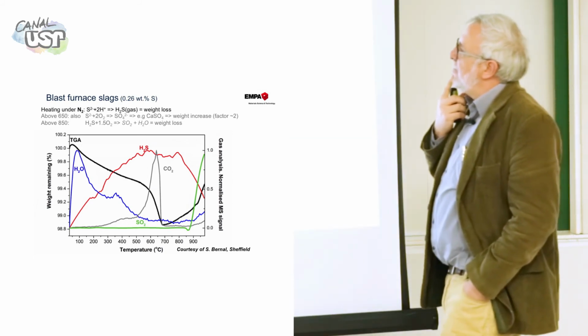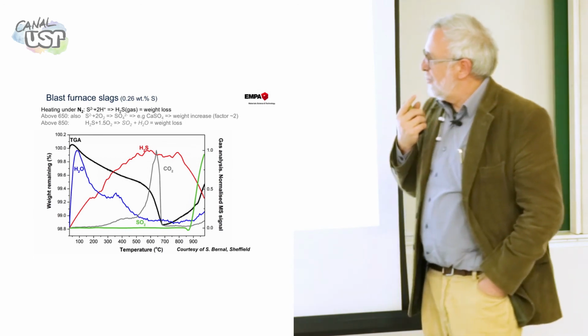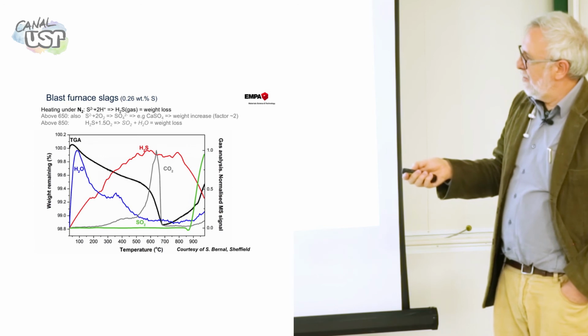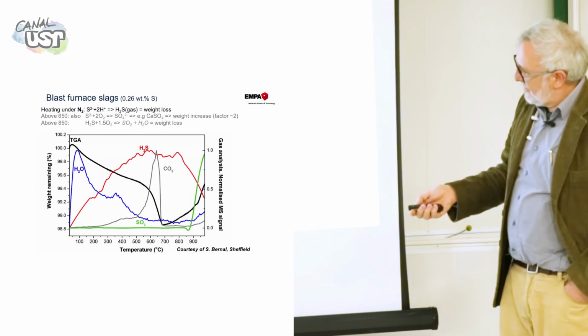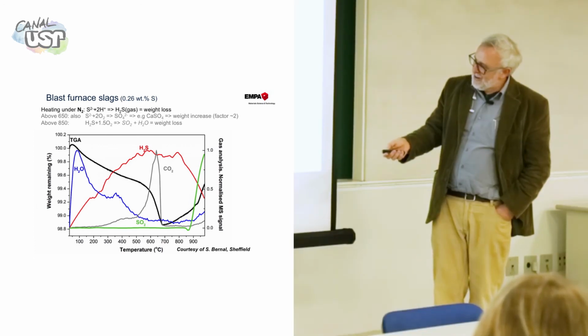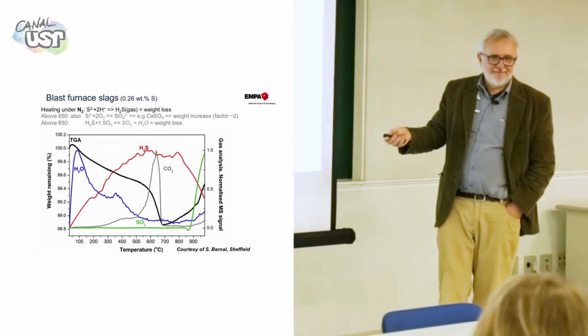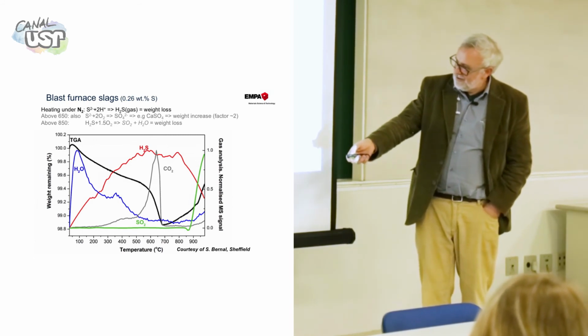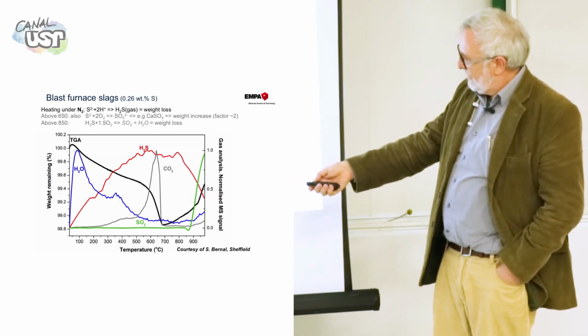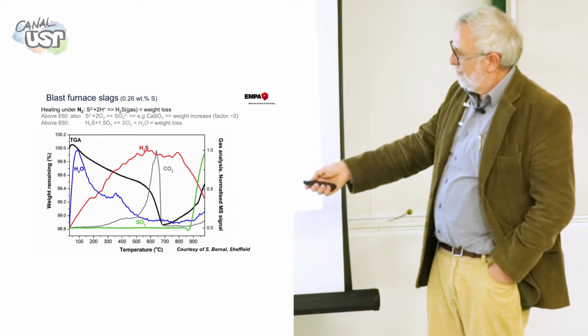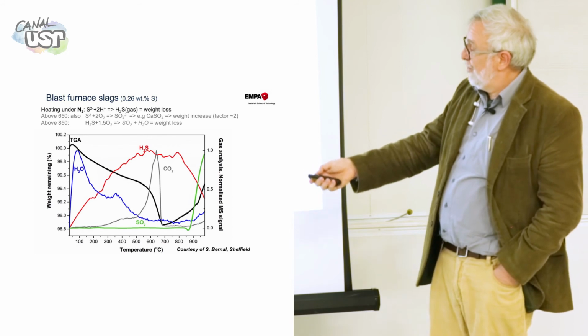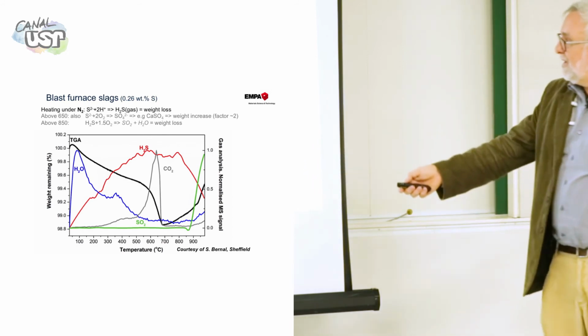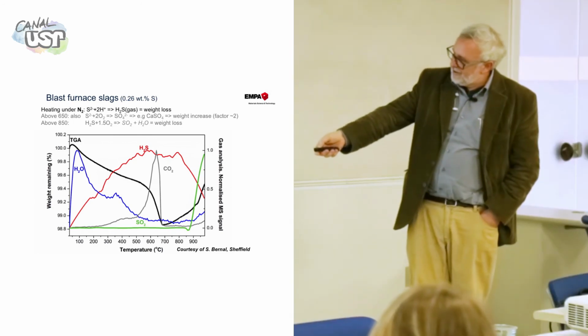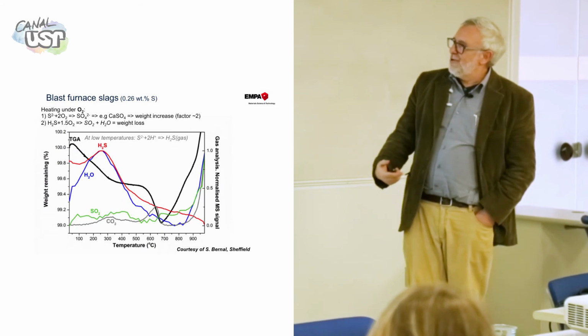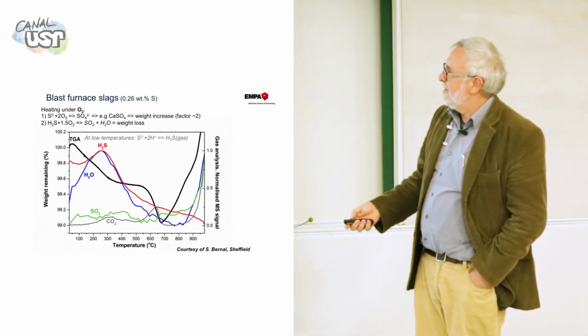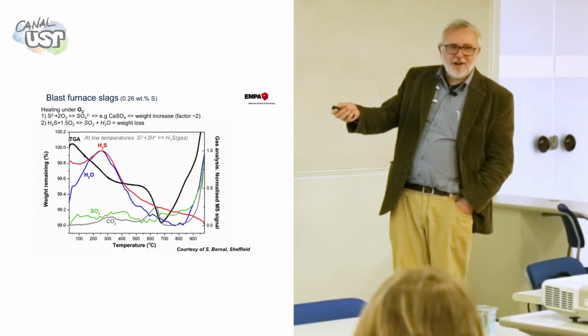Again, this is a mass spectrometry. So you are heating your cement. This is the weight loss, gravimetric. And at 650, the weight starts to go up again. And why? You see, sulfur oxide is coming out, and it releases, and it's going to increase the weight. So you should know that. Oh, so you see here, sulfur is going to be consumed here, and it's going to combine, and then the weight goes up. So what you have to do is, this is in nitrogen, then you put in oxygen, it even goes much higher. Yeah?